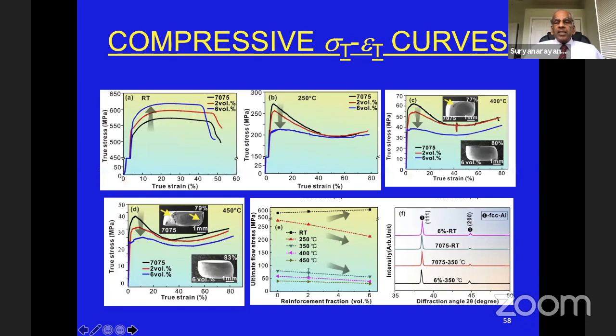But there is an interesting phenomenon occurring in this. If you plot the compressive stress versus strain, true stress versus true strain curves, you can see there is going to be some sort of a reversal taking place. The black line here represents the pure 7075 and is 2% and 6% of the metallic glass particles. This is at room temperature.